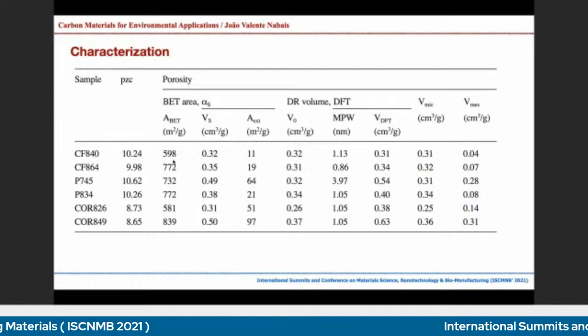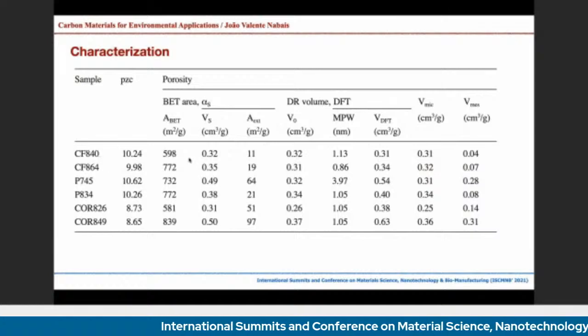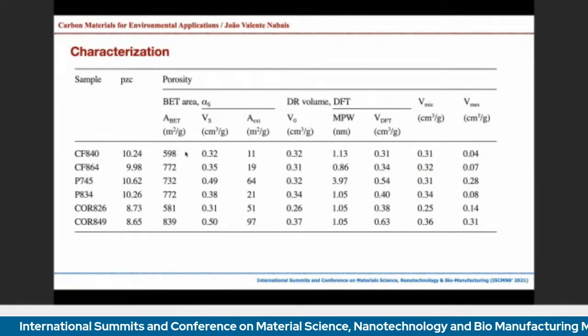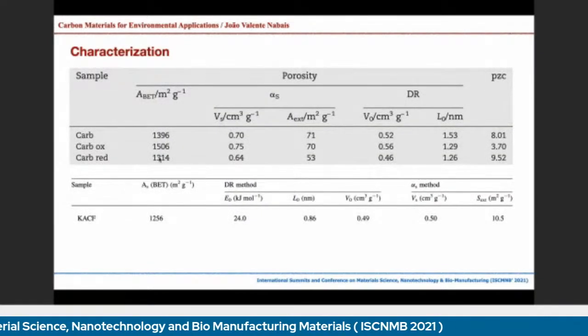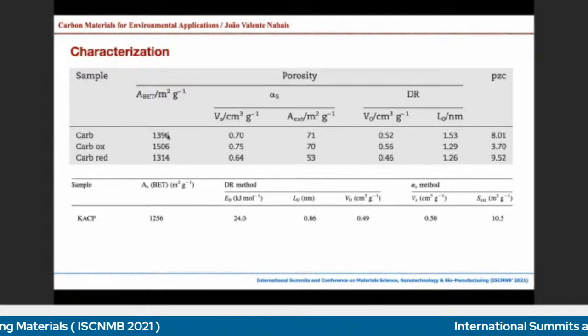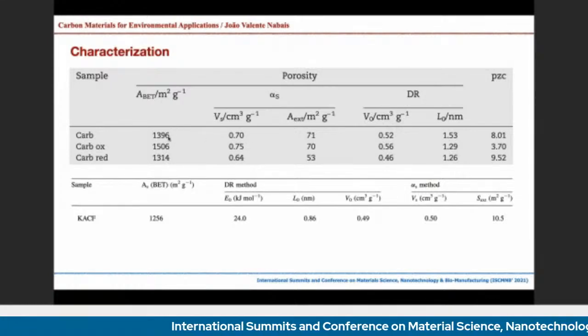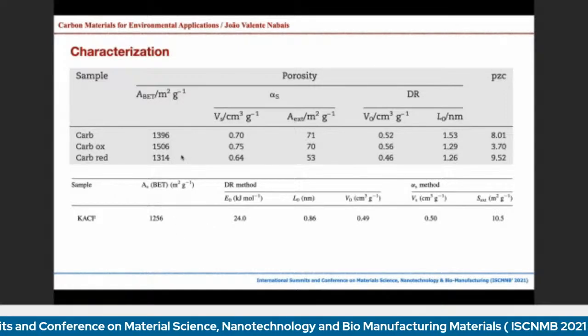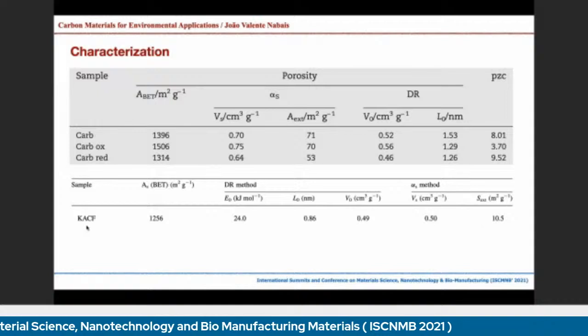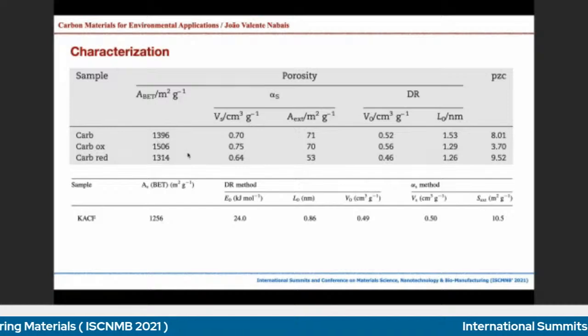So it means that these materials can be very interesting to use in studying the adsorption of inorganic pollutants and pharmaceuticals, as I'm going to show you. Regarding the commercial products, you can see here that the surface area and the porous structure is a bit higher than the material that we have produced. So when we compare the commercial products with our own products, we have to take this into account as well.